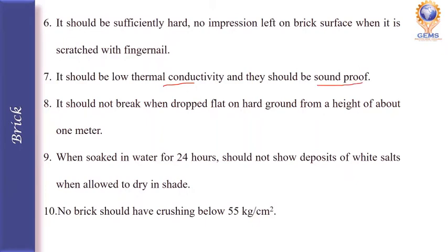If you drop the brick from 1 meter height, it should not break. If it is broken, then the brick should be rejected. Next, if you soak the brick in water for 24 hours and then dry it in the shade, white salt should not be deposited on the surface of the brick. If it is deposited, then we have to reject the bricks due to efflorescence.